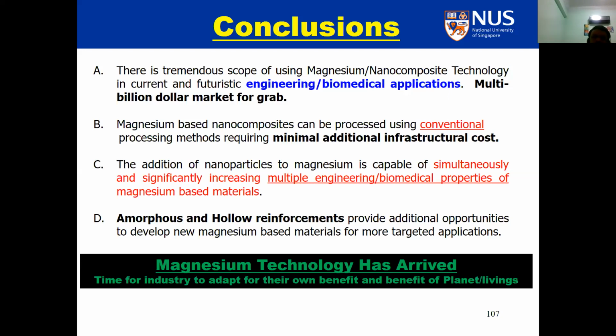You can use the conventional processing methods that already exist to melt aluminum, for example, and you can easily replace it with magnesium with minimal tweaks. So there's no additional infrastructure cost per se. Then if you use nanoparticles, for example, you can also help in improving many properties together, and that is exactly very important for engineering and biomedical application of this material. And as I say, there are other reinforcements, amorphous reinforcement, which leads to the metastable composite, and hollow reinforcement, which leads to the syntactic composite, that are also being pursued.